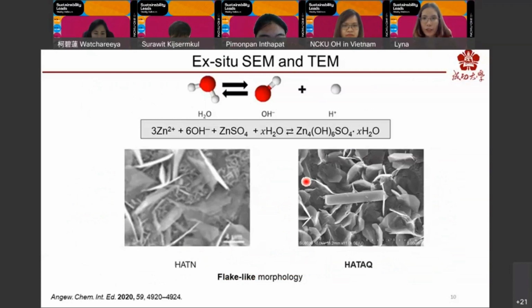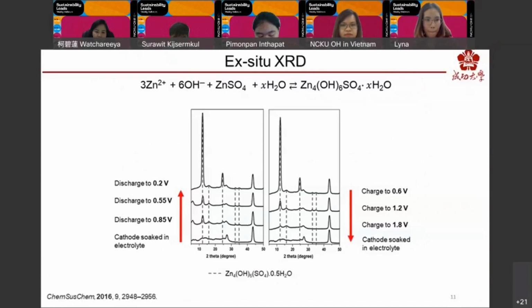As I have mentioned earlier, a large amount of hydroxides is also formed together with proton. Considering other reports, the formation of the new product on the electrode surface can be identified as zinc hydroxide sulfate with a flake-like morphology as shown in SEM images. Besides, the strong signals from ex-situ XRD are important evidence for the formation of the byproduct. During the discharge process, the peaks from the byproduct gradually become stronger, while they appear much weaker at the end of charge, implying the reversible structural evolution of HATAQ.